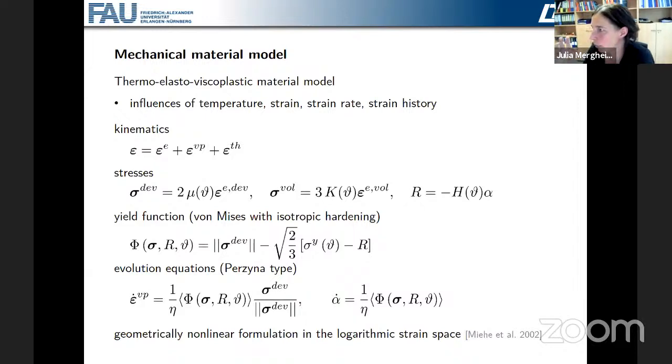What you have to do is that you get out the C, from your finite strain simulation, this F transpose F. Then you do a transformation of that to the logarithmic strain space. Then you get out this logarithmic strain. With that, you go to the material model. And in the end, the stress that you get out, you have to transfer that back to the, let's say,